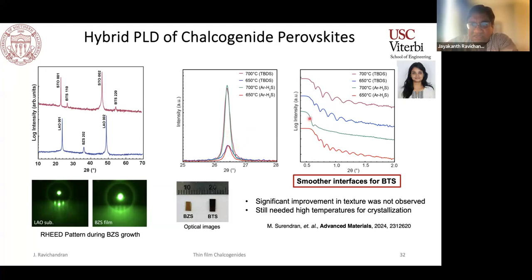What we noticed is this interface smoothness does get better when you compare the argon H2S technique to the hybrid PLD. And when you use hybrid PLD, it seems to be a lot more benign in the reaction with the interface of your substrate compared to the argon H2S, where presumably the argon that is ionized tends to really attack the substrate and the film and make it much more polycrystalline. But the amount of improvement that we were expecting was not observed, so it probably says something fundamental